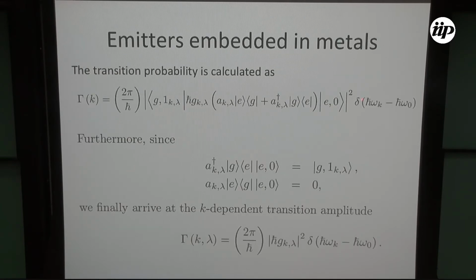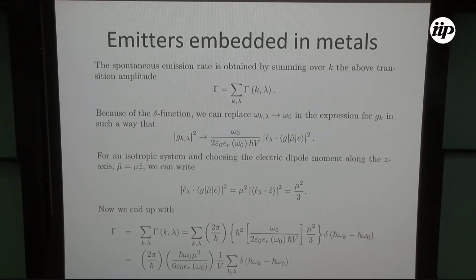We do this with the Wigner-Weisskopf Hamiltonian, we make use of the algebra associated to creation and annihilation operators, and we end up with this result. It's very convenient: 2 pi over h bar, a matrix element squared, and a delta function here. But in order to get the transition rate, I have to sum over all final states labeled by k and lambda. The matrix element squared just gives me the projection of the dipole moment in the direction of the polarization of light. For an isotropic system, this is simply mu squared divided by 3.